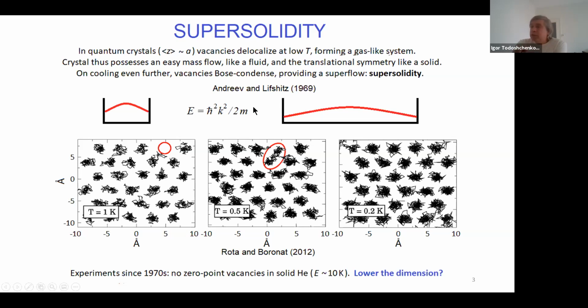So the basic thing is to realize that a vacancy delocalized over the whole crystal sample is actually the ground state of the vacancy. In order to localize a vacancy, you need finite energy. This is very clear from this picture of the particle in a box. The lowest energy of the particle in this box is proportional to the square of the lowest wave vector, and in a larger space, the lowest energy is lower. So this is the ground state, and to localize a particle, a vacancy, you need finite energy. So delocalized vacancies are ground state properties in quantum crystals.